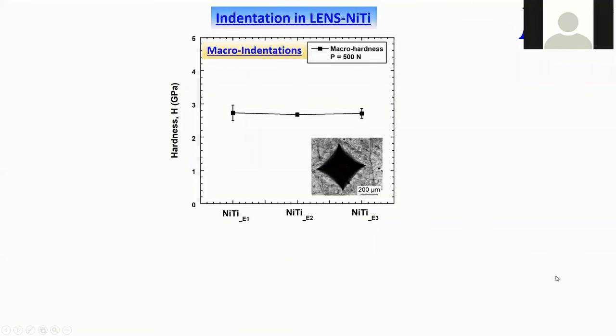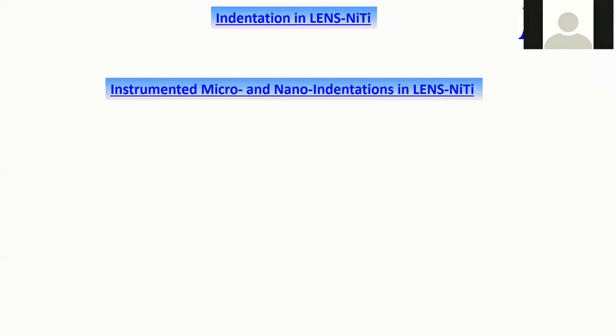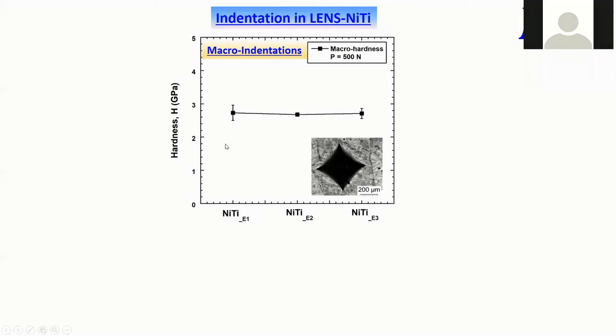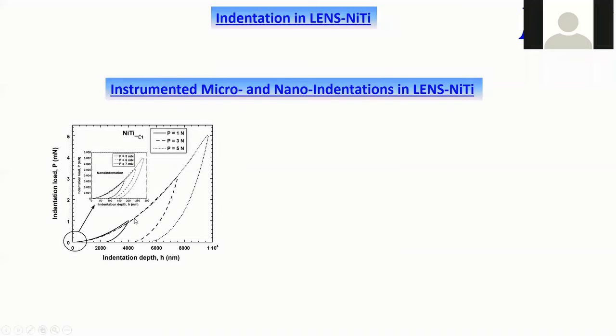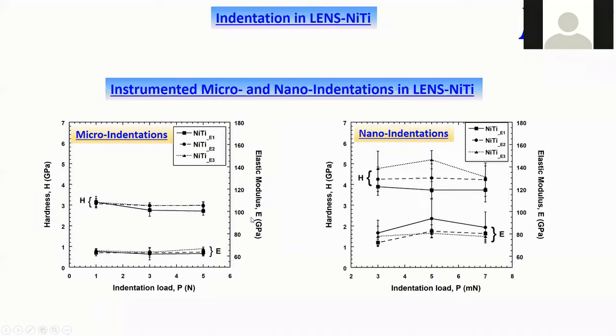particular alloy. So with this information on the basis of the microstructure, we did the indentation study at the first hand. Macro indentation does not show us much variation in the properties, but if we do this as micro and nano, especially at nano, we have seen some variation in the properties, and we particularly have seen some changes in the values for the alloy which is being prepared with an energy in between the high and the low value. Okay, so from microstructure, we could not say much about the properties that it is going to generate.